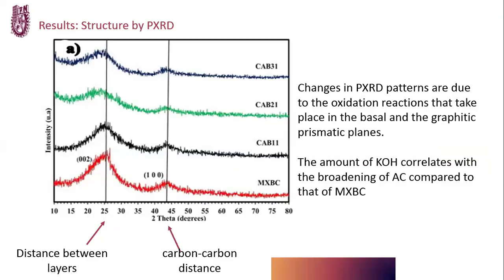Now let's see the characterization of these samples. The diffraction patterns of the samples show amorphous characteristics. The most intense peak at 25 degrees corresponds to the distance between layers. The less intense peak at approximately 43 degrees 2 theta corresponds to the carbon-carbon distance. Changes in powder X-ray diffraction patterns are due to the oxidation reactions that take place in the basal and the graphitic prismatic planes. They are more evident in this first peak.